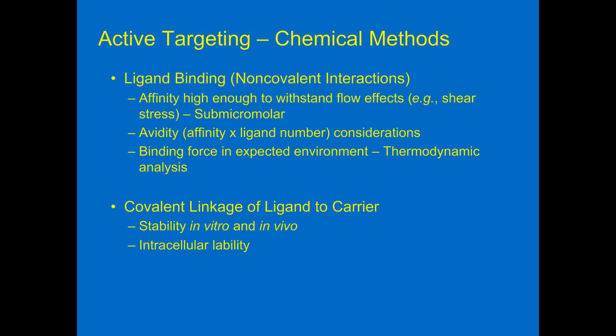For instance, if you have an entropic association, which is going to be hydrophobic, then you're going to get the maximum binding strength in an aqueous environment. Whereas if your binding is going to occur in a relatively apolar environment, then you'd be better off with a highly enthalpic interaction, which would involve ionic interactions. So you'd want charges and so on.